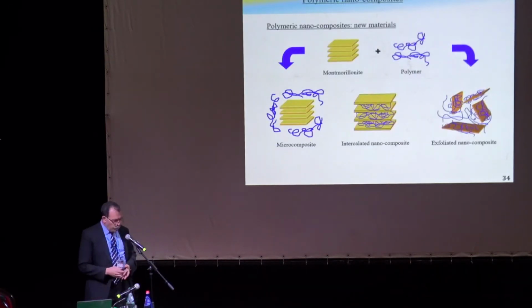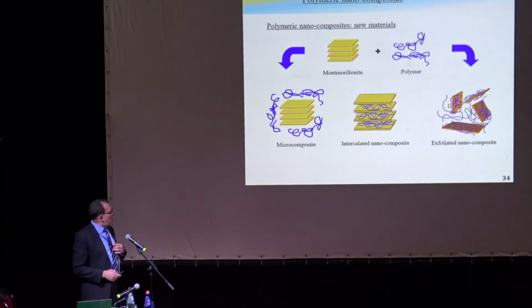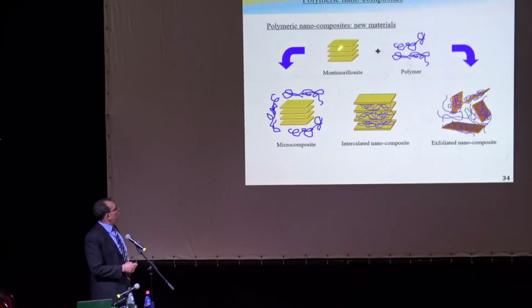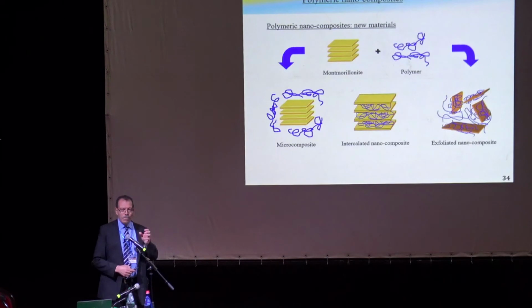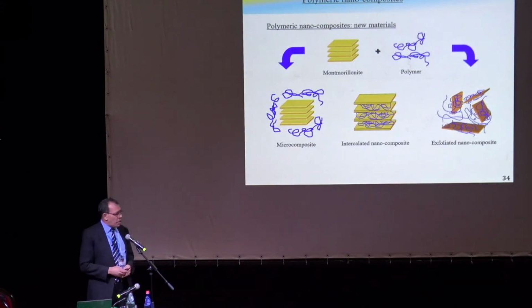Yeah. Now, I move to the nanocomposites. We did some work in Strasbourg with a couple of students on the polymers reinforced with the nanoclay. And the nanoclay comes into particles like this. When you mix with polymers, depending on the mixing conditions, you may get nothing happens. You still have this micro composite or micro fillers, or intercalation, okay? And this is now much better, so we go to nano somehow. But the best morphology, or microstructure, is if you get full exfoliation.